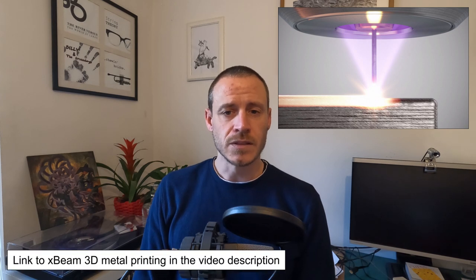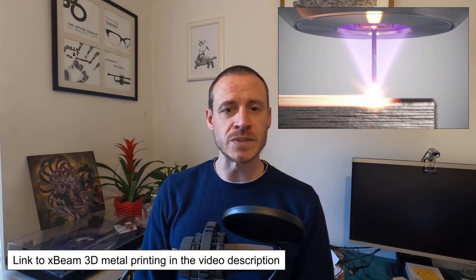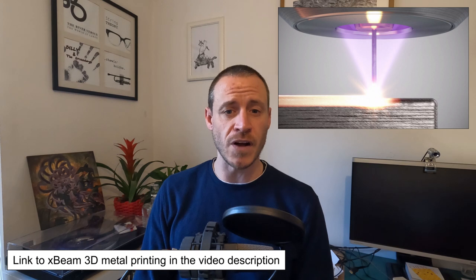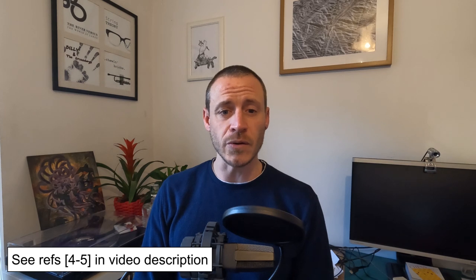X-beam is a direct energy deposition additive manufacturing process that uses a hollow conical electron beam to melt wire that is fed coaxially through the conical beam. This unique process creates favorable deposition conditions to promote refinement of the large beta grains in Ti64 and is known to produce equiax grains instead in X-beam components. However, these equiax beta grains have only been studied optically and a texture analysis has never been conducted.